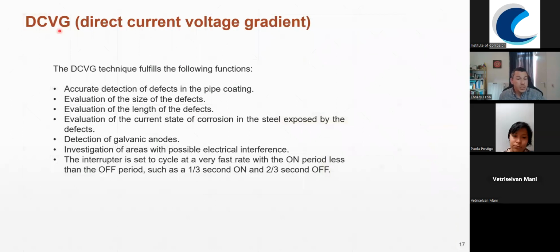So DCVG is a direct current voltage gradient. This one helps us to have an accurate detection of the defects in the pipe coating. The target of the DCVG is not to say anything about cathodic protection, but cathodic protection and coating is a perfect marriage. So we need to make sure that both are okay. If we want to have a CP system working properly, our coating system should also be working properly, should be in good shape. So that's why DCVG is so important to assess CP.